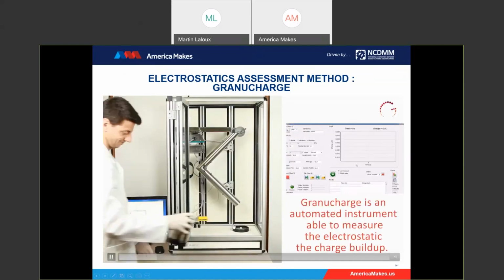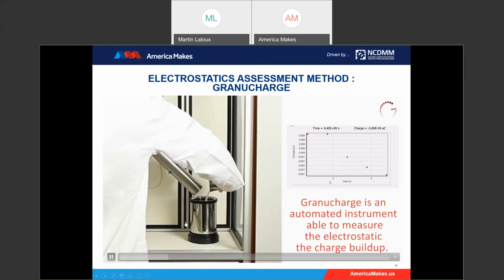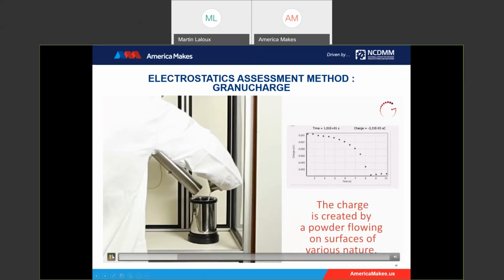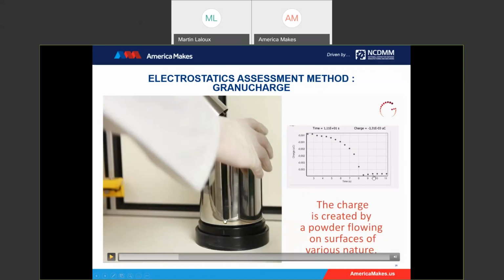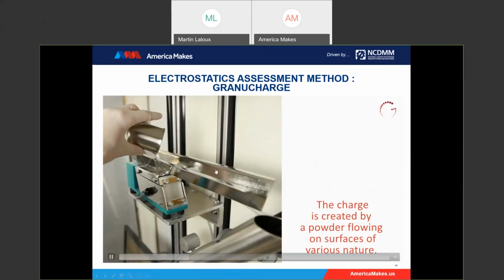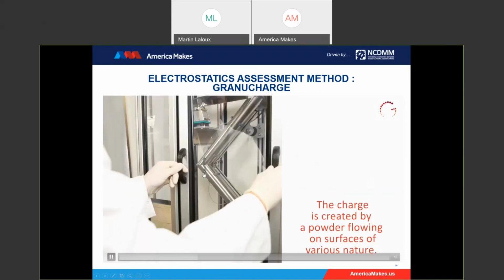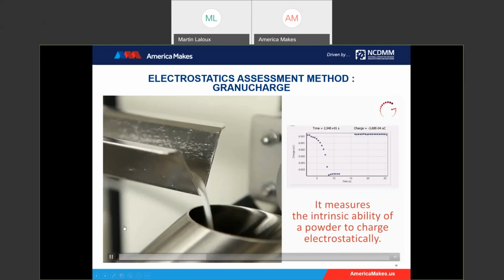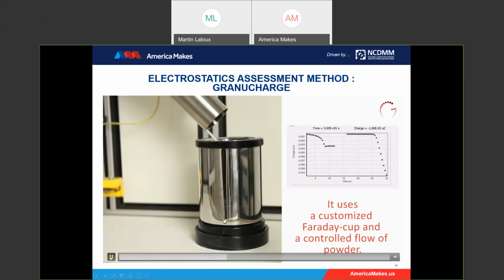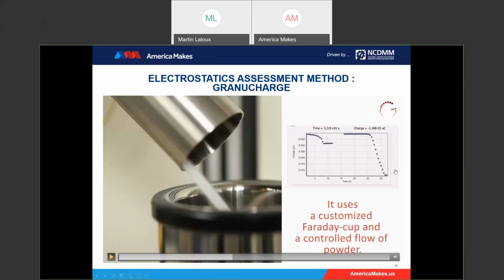Here you have the charge, and then we have a Faraday cup. We measure the initial charge in the powder, because due to shipping, storage, and so on, you might have some initial charge in the powder. In the software, you can see we measure the time and the charge. When we reach the plateau value, this is the initial charge. Then we pour the powder in the feeder. We close the door because you can control the humidity inside, and we start the flow. The powder will acquire some charge between particles, but also between particles and the pipes. Then you get at the end the same plateau value. This is the final charge after the flow through the pipes.